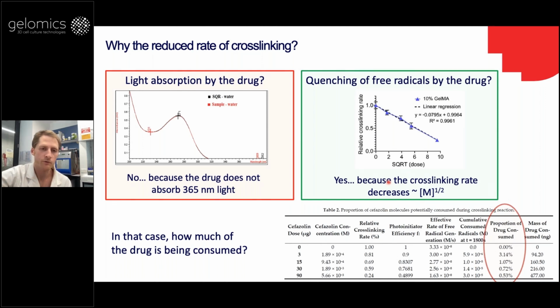So using the characterization that we've done before in terms of the number of radicals that are being produced, you can actually work out, if this is what's happening, how much of the drug is being consumed. And you do all the calculations in molar values. The risk is that if your drug is quenching the reaction, then maybe all the drug is getting used up during the reaction, in which case you won't have any left over to release to deal with the bacteria. But it turns out that when we run these calculations, we see that only a couple of percent of the drug is actually being used up in this quenching process, and the proportion actually changes depending on the concentration.